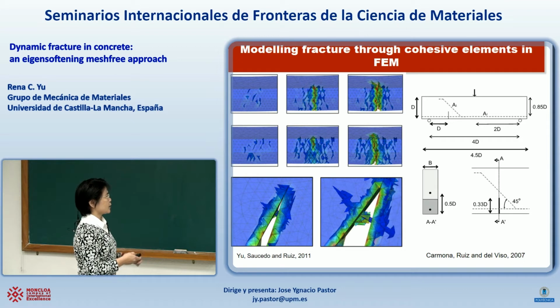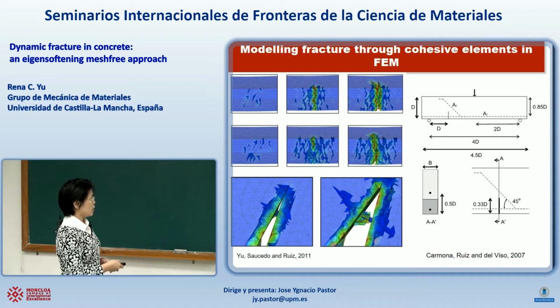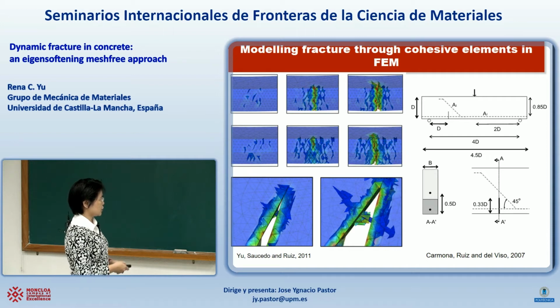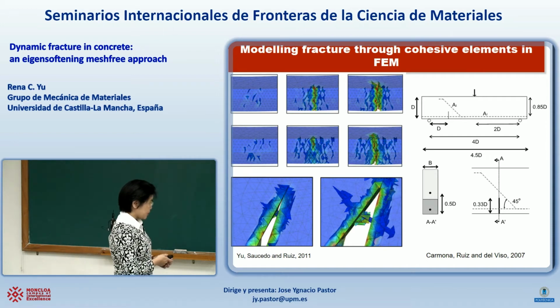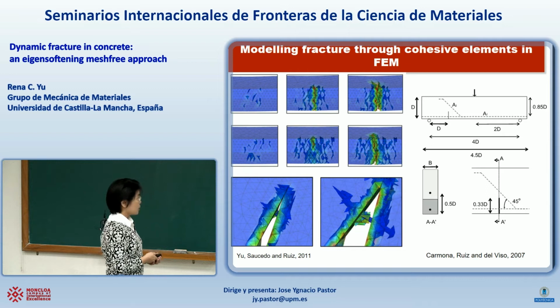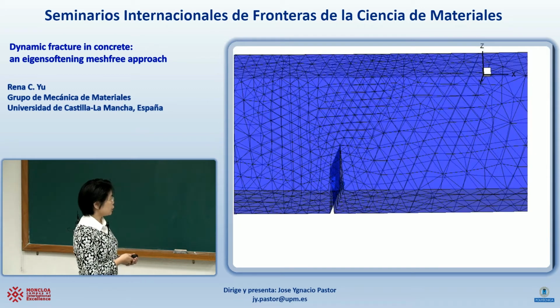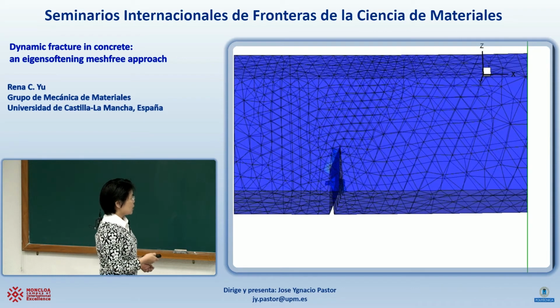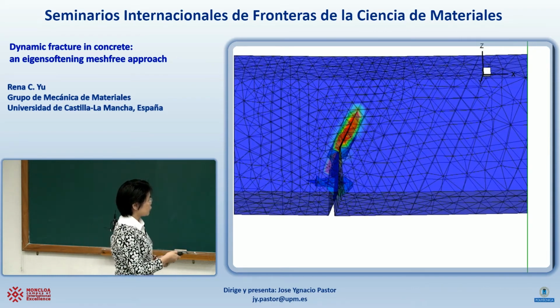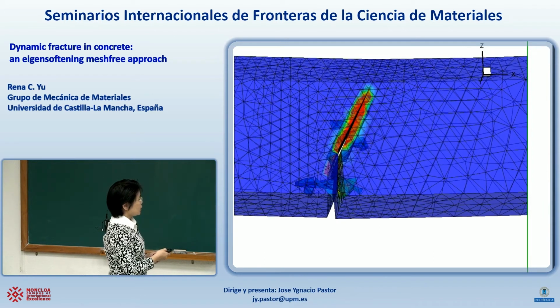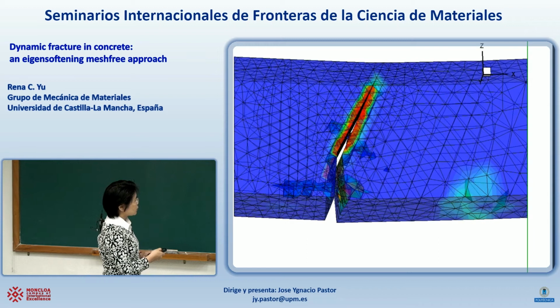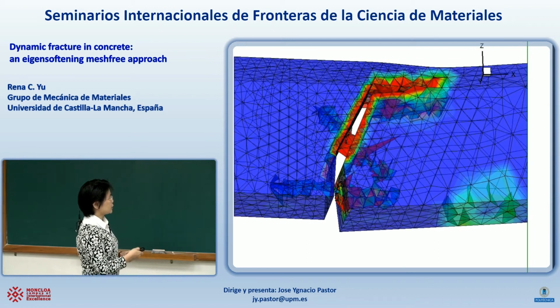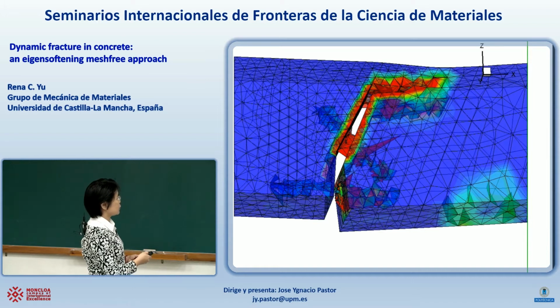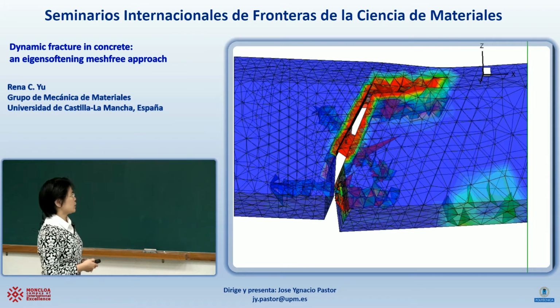the experimentally tested beam. There's our transversal rebar here. We see how the fracture initiated from the notch and propagates away. The following is a video to see how this crack propagates. You see this is the longitudinal rebar, and this is the crack, which propagates along the element boundaries, and this is a transversal rebar. The red color corresponds to a crack that has become a stress-free crack.